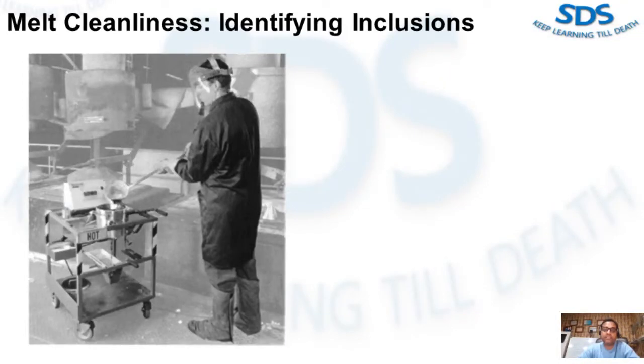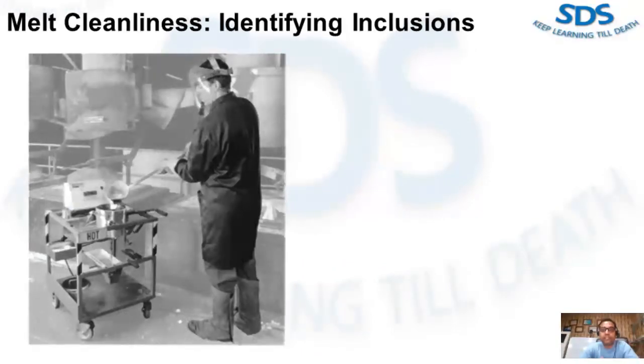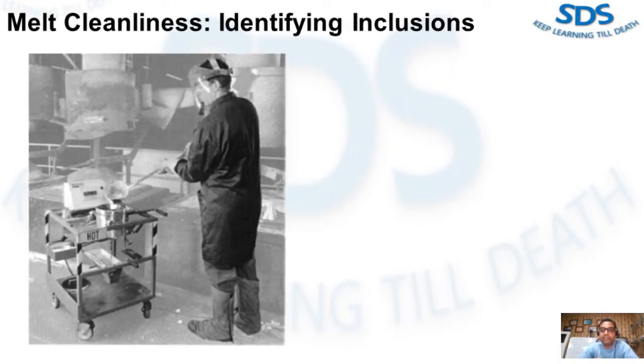The first shop floor technique is a simple fracture test. By observing the fracture surface of a solidified cast sample under a low power microscope, one can see the presence of inclusions. One popular form of such test involves the K-mold. A step bar permits easy fracture at the knife point. Generally, 4 samples of 5 fractures each rate the inclusion rating, determined by the number of simple visual inclusions observed divided by 20. Only macro inclusions about 400 microns or larger can be observed with this technique. A trained operator can assess metal quality relative to an established process standard and determine if further melt treatment is required.